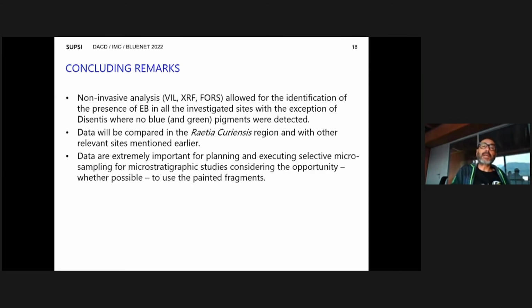So these are some concluding remarks. These are well-known things to the Bluenet community, that non-invasive analysis such as VIL, XRF and FORS allowed for the identification of the presence of Egyptian blue in all the investigated sites, with the exception of the Disentis, where no blue and also no green pigments were detected. And this data will be compared in the Raetia Curiensis region and also with other relevant sites mentioned earlier, because we have evidence of the fact that, for instance, in San Saba in Rome, Egyptian blue was mixed with natural ultramarine, and copper comes from a pure source.